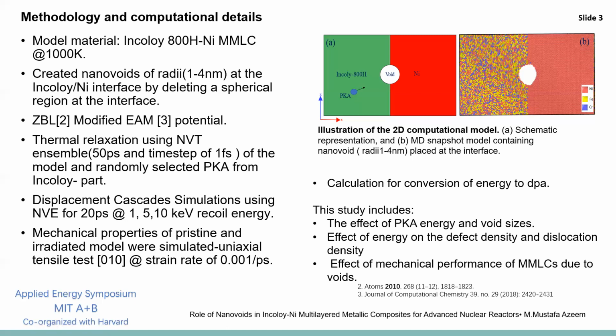Later, the mechanical parameters for the pristine and irradiated samples were determined at 1000 K using the uniaxial tensile simulation along the y-axis at the strain rate of 0.001 per picosecond. The calculated properties include the ultimate tensile stress, ultimate strain and Young's modulus for each of the sizes in the later slides.